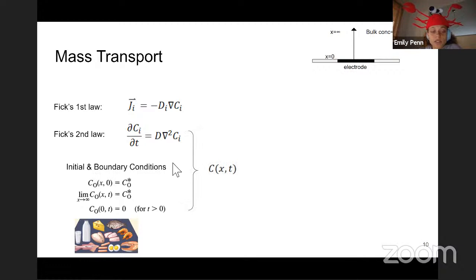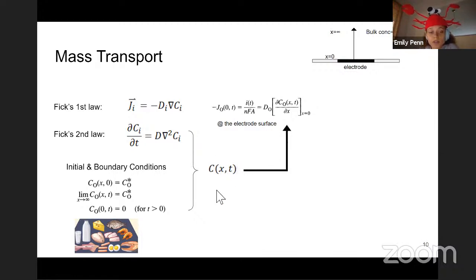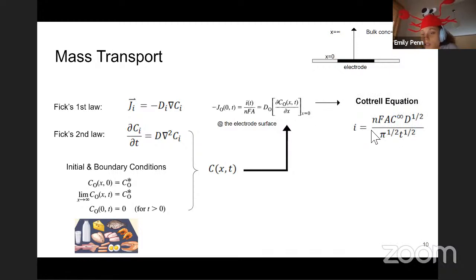When we apply these initial and boundary conditions to Fick's second law, which is the diffusion equation, we get the concentration of our species as a function of position and time. Looking back at Fick's first law, we can say that the flux at the electrode surface is related to the current, and this is a function of the concentration gradient, again, like we saw before. And now that we have the concentration as a function of position and time, we can use this in Fick's first law, and we arrive at the Cottrell equation.